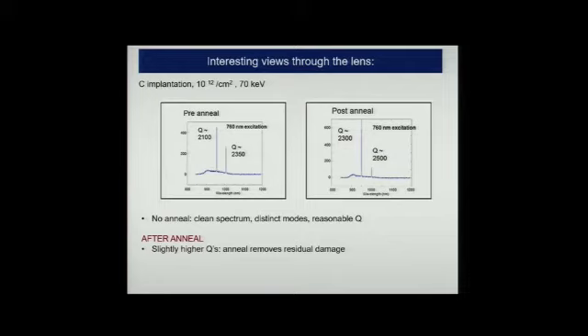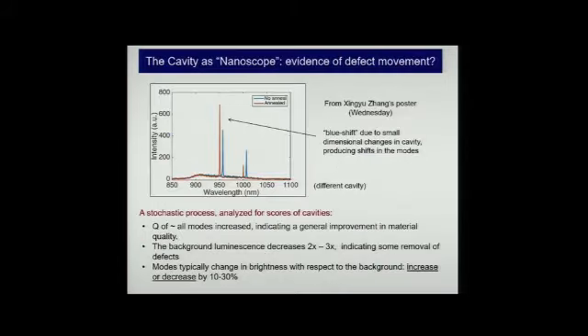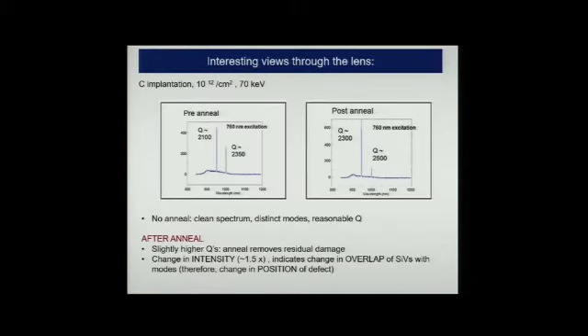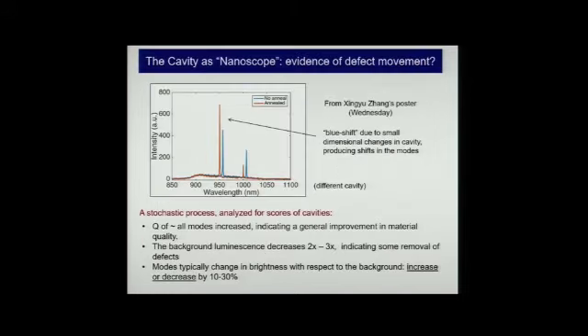Our supposition is maybe the anneal was able to get this higher intensity because we pushed some of those emitters into slightly better spatial location with respect to the electromagnetic field. So our change in intensity, we think, is a change for the better in the overlap of silicon vacancies with the mode. Now, this is stochastic. Not every cavity showed an improvement. Some cavities showed a decrease, and it would have to, because this is largely by chance.